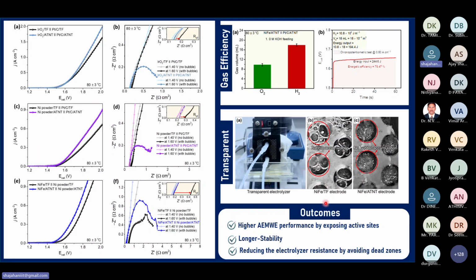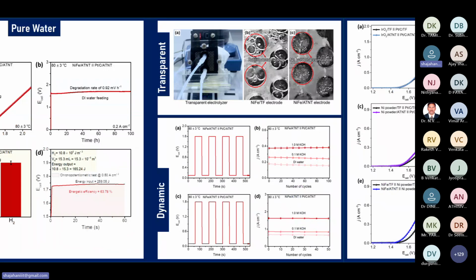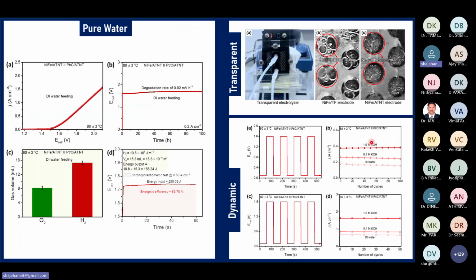When we use the TF based one and the ATNT based one, you can observe bubble accumulation in the TF based one. But in the ATNT based one there is almost no bubble accumulation; the bubbles release quickly. So from here we observed that the super hydrophilic nature of ATNT shows better gas release than the TF based one. Once we used KOH solution, later we tried pure water also.